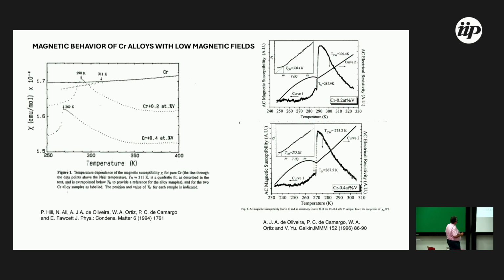Okay? This is my first paper in my life, 1994, but I studied this problem today. And this curve is the same experiment, but not the DC susceptibility, but AC magnetic susceptibility. AC magnetic susceptibility applies a field that depends on the frequency. In this case, it is a low frequency, 40 Hertz. This is interesting because two components are observed in these measurements: a component associated with magnetic behavior and a component associated with resistivity.